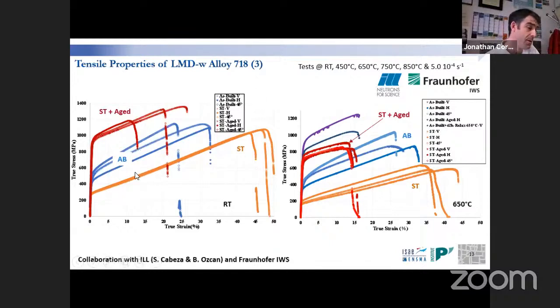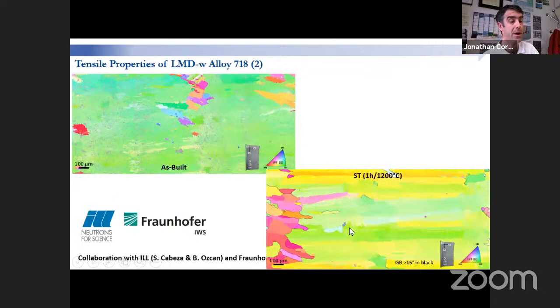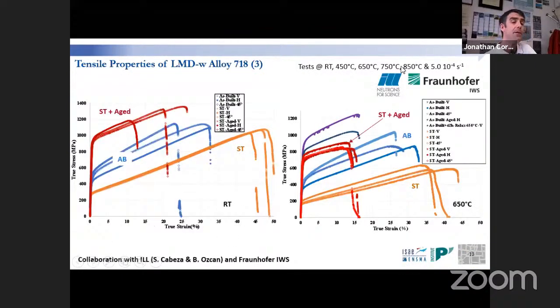So it means that we have an increase of properties provided by the non-negligible fraction of Laves phases. And then when we introduce the precipitation of gamma prime and gamma double prime, we can see another increase, which was expected from the beginning. Still, the yield stress here is quite low in comparison to a forged alloy due to the very, very large grain size. You have to keep in mind that typically we have columnar grains, and a grain size in this direction typically in the order of 100 to 200 microns, and very, very low neighboring misorientation.